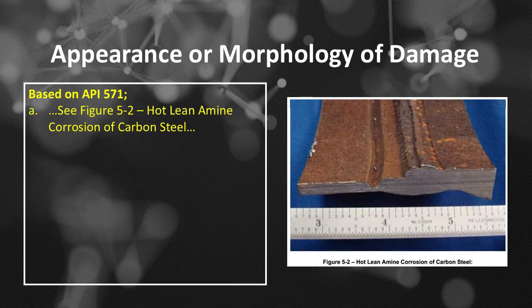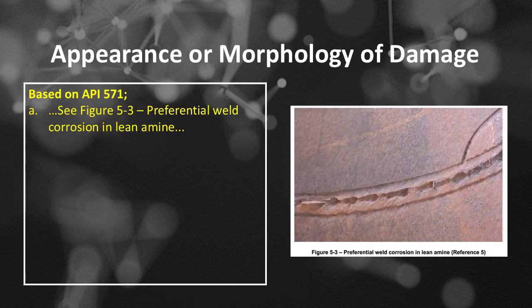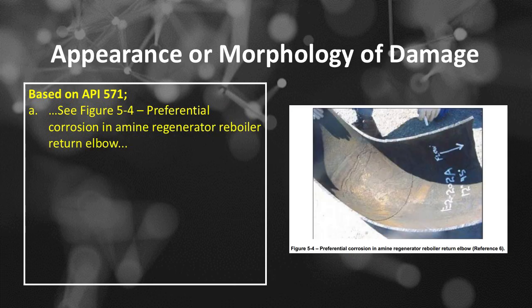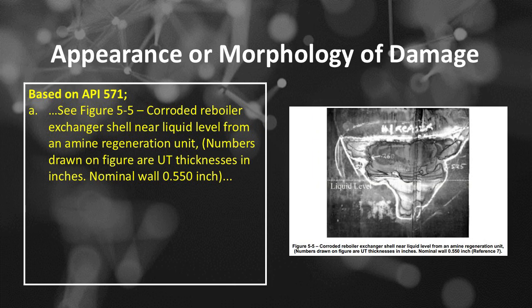They were originally found and mistaken as cracks with shear wave UT inspection. See Figure 5.2, hot lean amine corrosion of carbon steel. See Figure 5.3, preferential weld corrosion in lean amine. See Figure 5.4, preferential corrosion in amine regenerator reboiler return elbow. See Figure 5.5, corroded reboiler exchanger shell near liquid level from an amine regeneration unit. Numbers drawn on figure are UT thicknesses in inches.